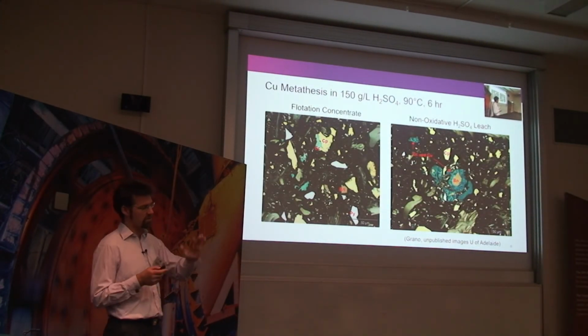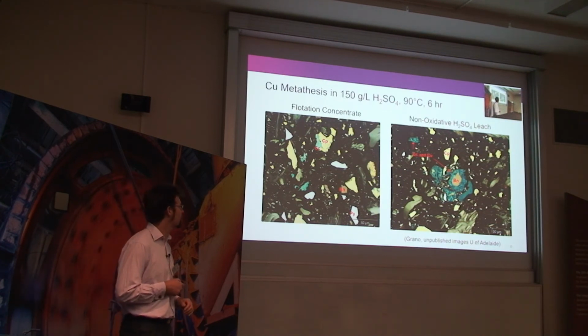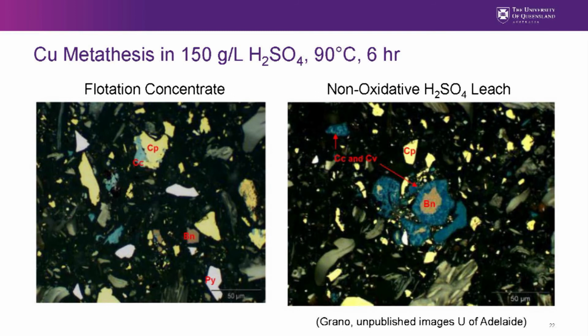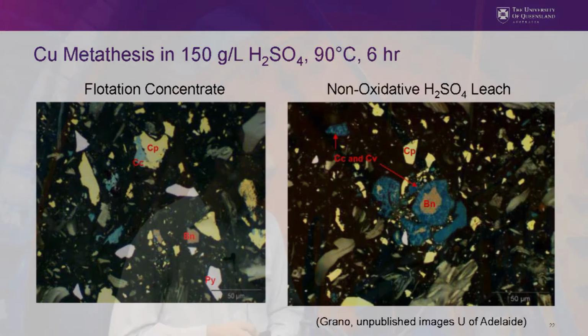Okay, so that was high temperature, so just cooling down now a little bit to 90 degrees. This is an example of copper metathesis reaction occurring at 90 degrees in 150 grams per liter sulfuric acid for 6 hours. It's a cross-section optical micrograph, which seems pretty handy for resolving the different copper mineral phases. And just to point out that even at 6 hours here at 90 degrees, we see a lot of bornite being converted to chalcocite and covellite. So the metathesis proceeds at low temperature and even at room temperature, just much more slowly and maybe much more mineral specific.